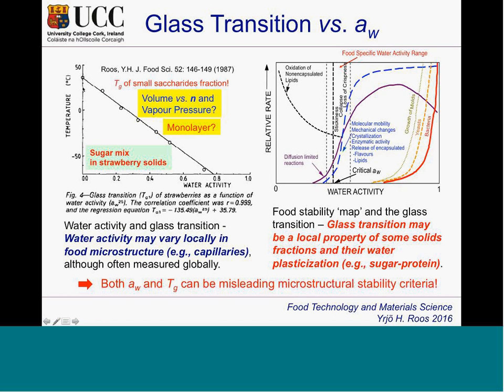They're nice, but if you expose them to a little bit of high humidity, not much more than 0.1 or 0.2, they really get wet and soggy, not nice any longer, not crispy, and there are quality changes. So I can say that there's something critical happening, and what we have done then is to add glass transition to the stability map, and we can then identify a critical water activity, where the temperature and glass transition meet,